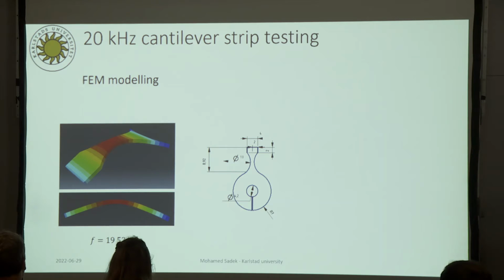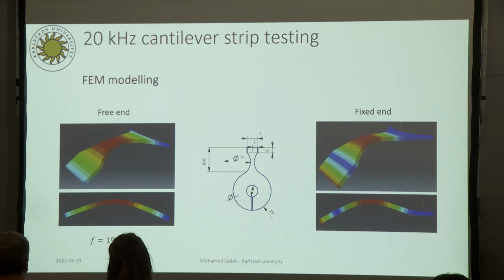However, after the testing was done, we realized that this simulation is actually wrong. You see the end here to the right is the end that is supposed to be clamped into the horn, or between the horn and the rod, and therefore it shouldn't have any angle there. It should be straight out. So the boundary condition in this simulation was wrong and wasn't realized until after the testing. We fixed that with the right boundary conditions, and then we realized that the actual frequency of the specimen is 25 kHz rather than 20.